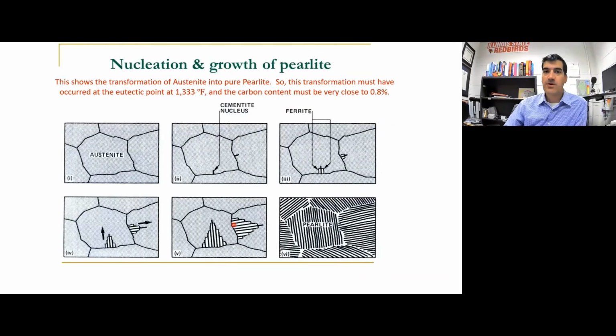All right, here's a couple more pictures of the transition. Here's what that transition looks like from all of our grains being austenite to just starting to grow some other grains. So this is a little cementite nucleus, and then it's going to start growing bands because this is going to grow into pearlite. So it grows some layers of ferrite and then some additional bands of cementite. And this is happening in multiple grains at the same time.